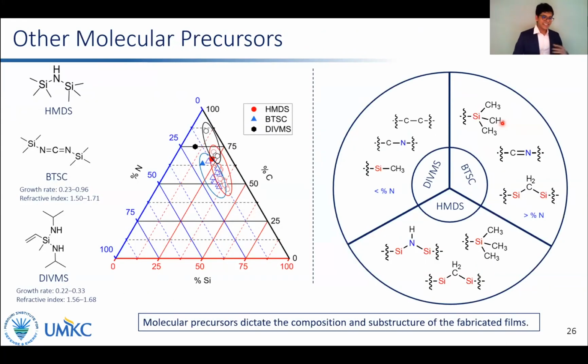So after completely analyzing the hexamethyldisilazane-derived silicon carbonitride thin films, we went on to perform similar analysis for the other two precursors using factorial design. We were able to tune the properties of these two precursors as well, similar to HMDS, and the composition was also weighted.